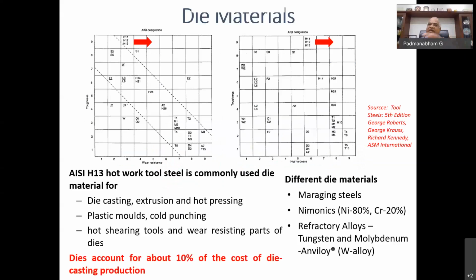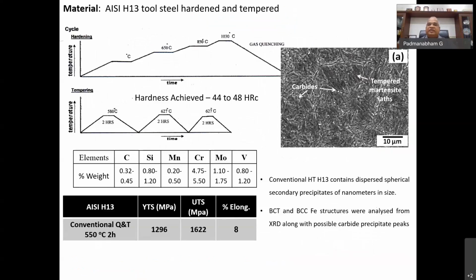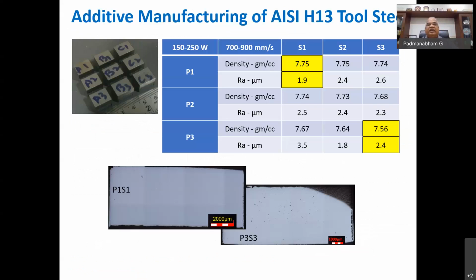And take the other materials, like the die materials, Maraging steels or the hot work tool steels like H13. Here you want high temperature properties. And normally to achieve these properties, you have certain very elaborate heat treatment cycles that you look for, a very fine distribution of the hard carbides, which do not coarsen but give you high temperature properties in the conventional method. When we did additive manufacturing of H13 tool steels, what I'm presenting is actual work done in our lab.